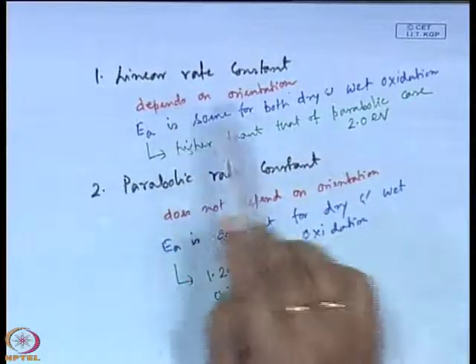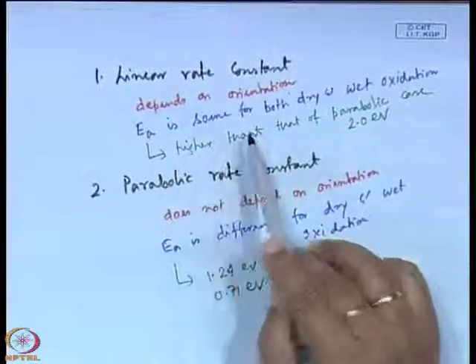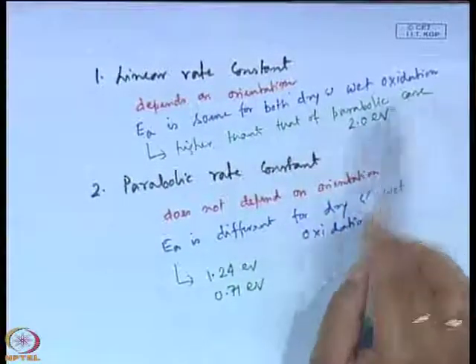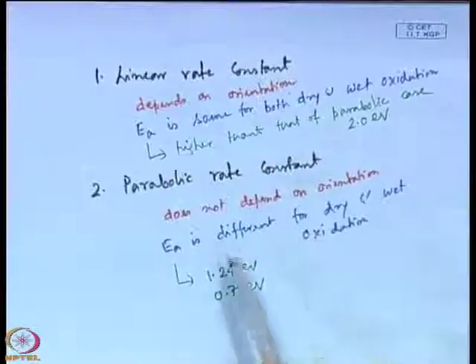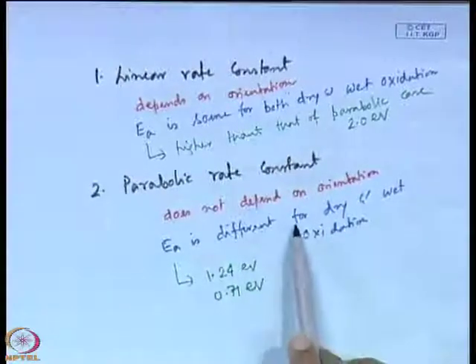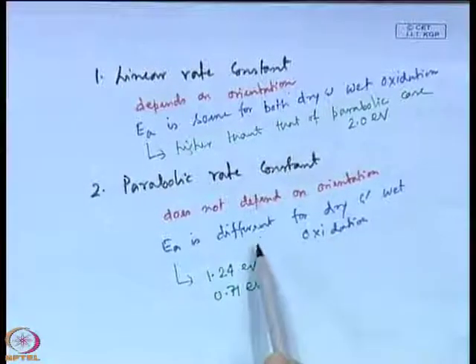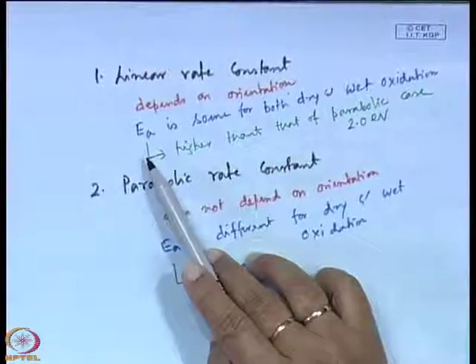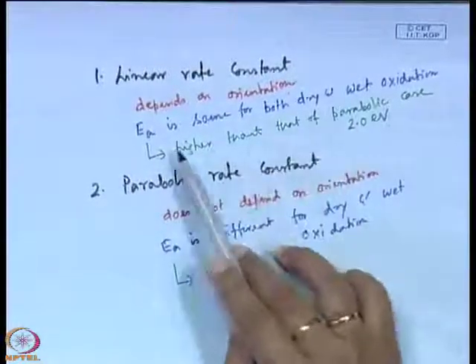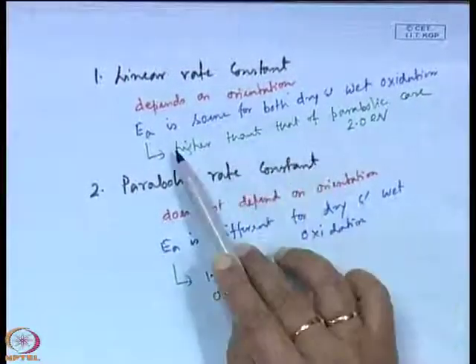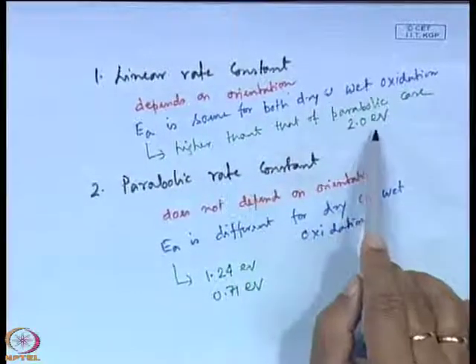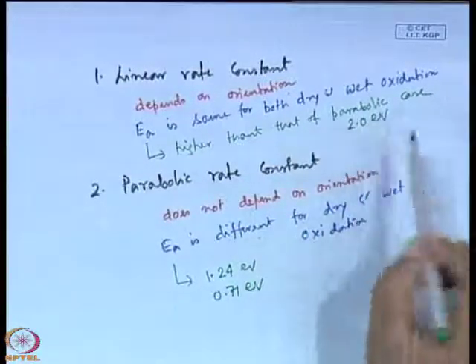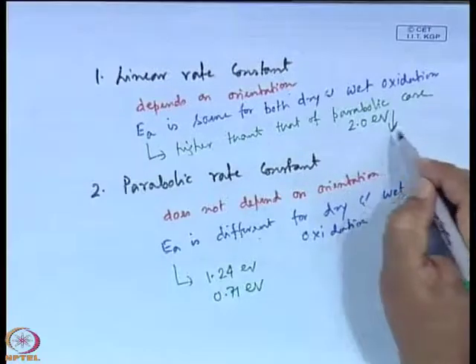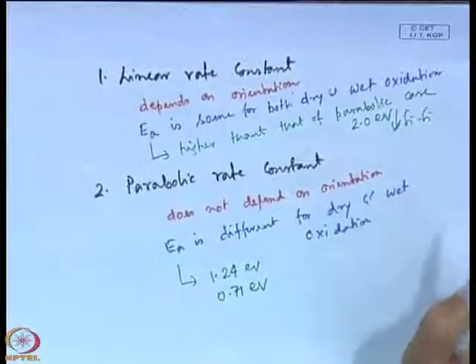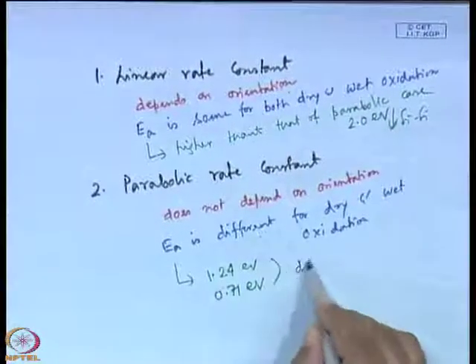Then for the linear rate constant, the activation energy is the same for both dry and wet oxidation. For the parabolic rate constant, the activation energy is different for dry and wet oxidation. The activation energy for the linear rate constant is 2 electron volt, which is higher. Why is it higher? Because this is the amount of energy required to break the silicon bond. Here, it is for the diffusion only.